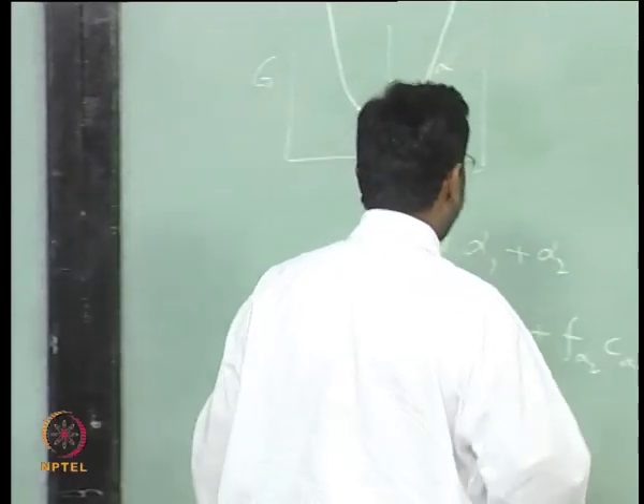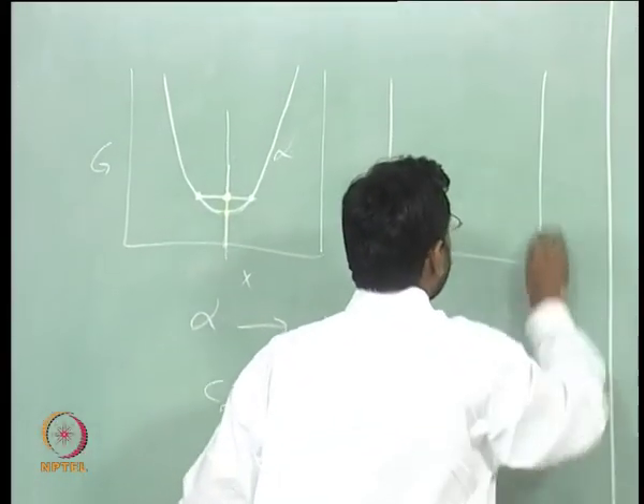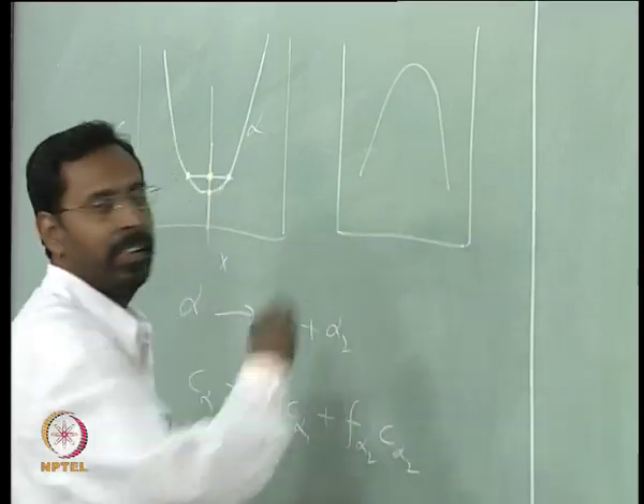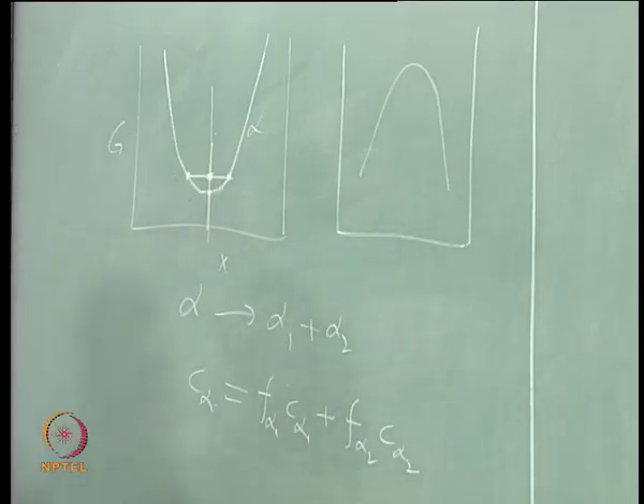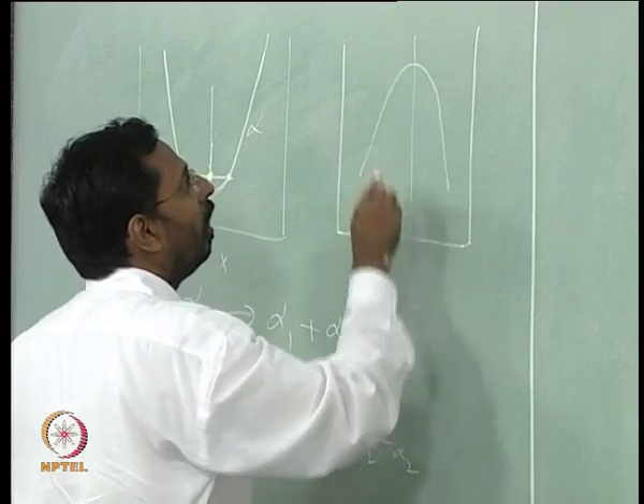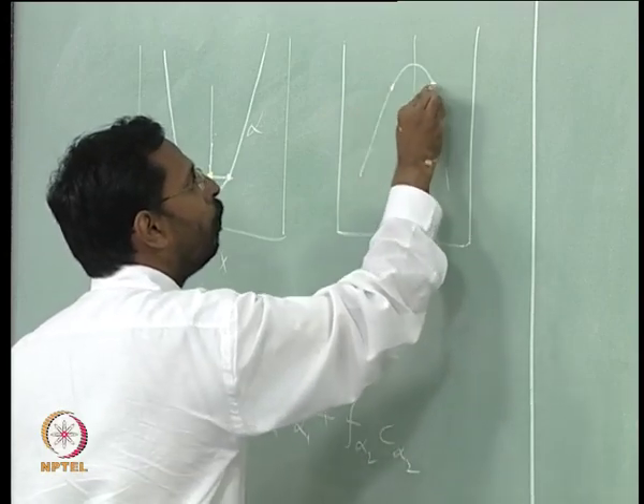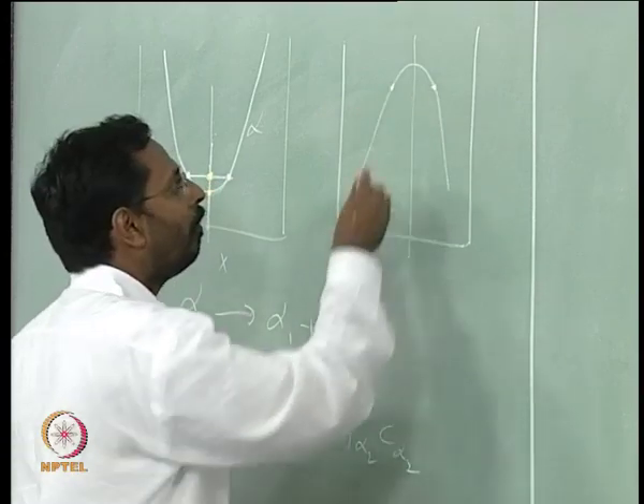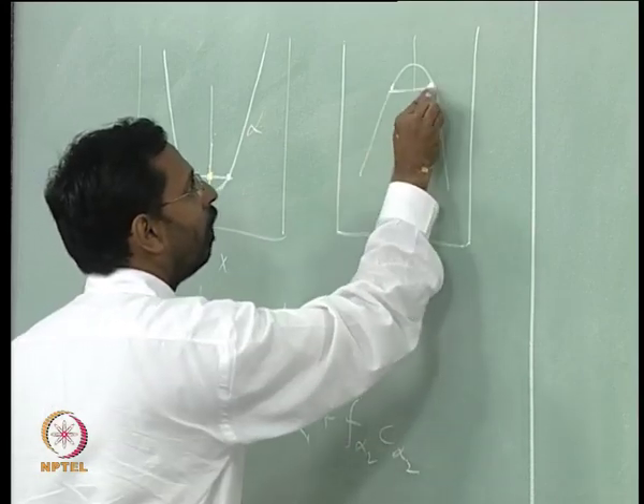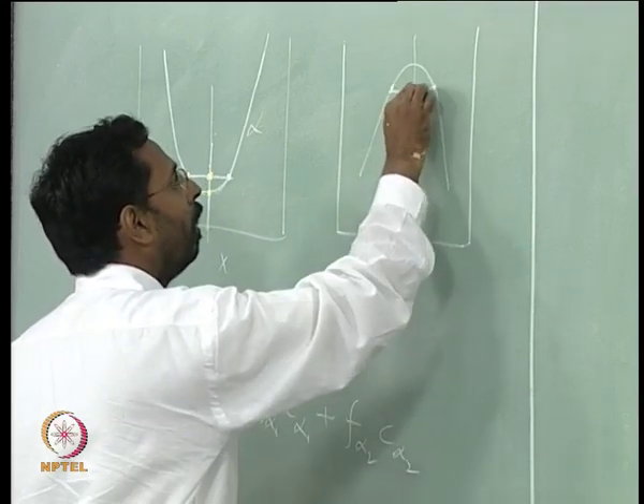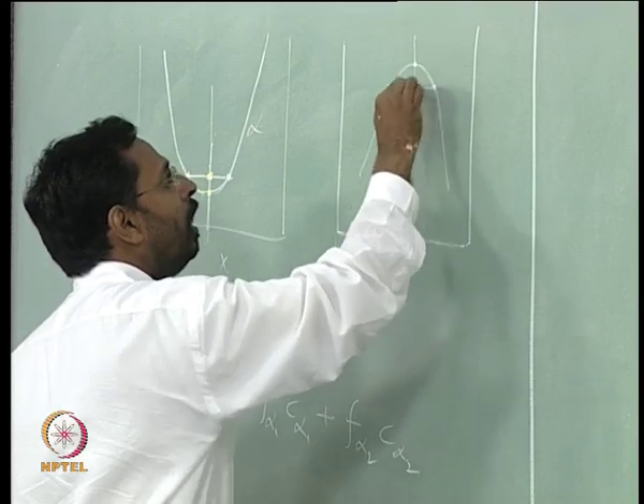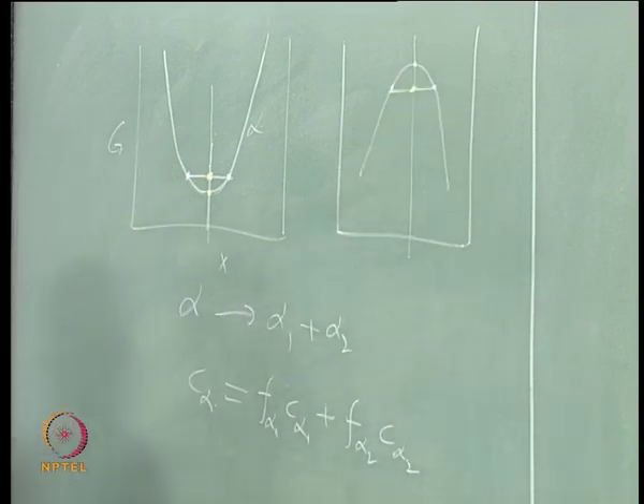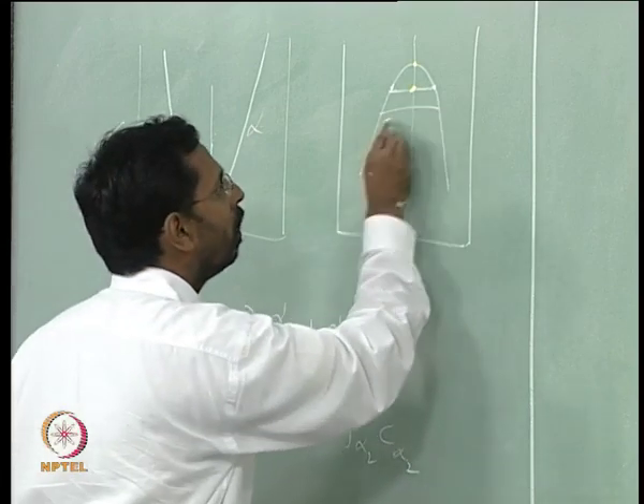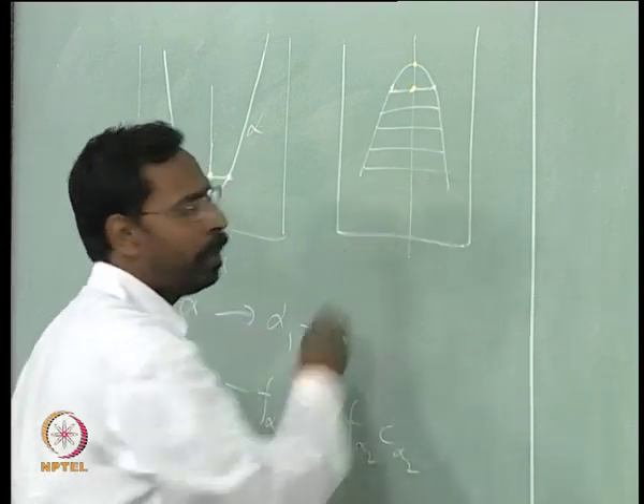But if your free energy curve is like this, then this alpha can split into two phases of alpha 1 plus alpha 2, and which have a free energy of this. So, from here to here it can split, and it can not only split like that, it can keep on splitting more and more.